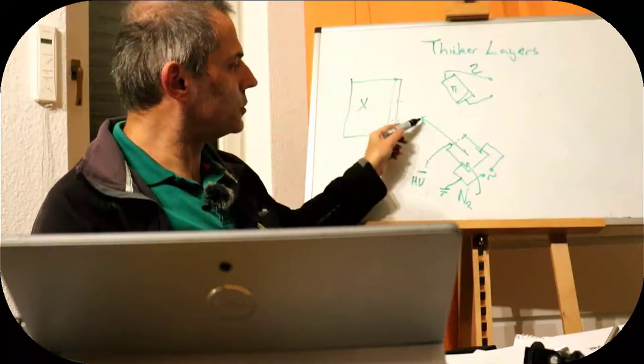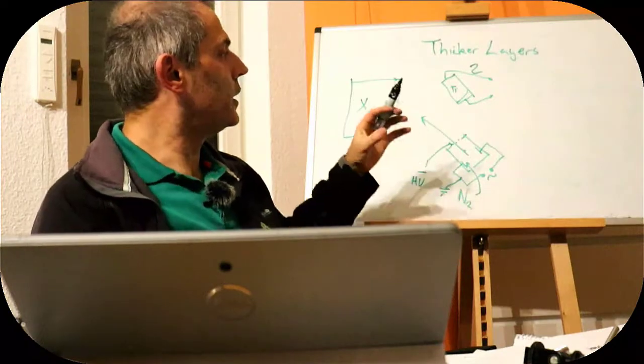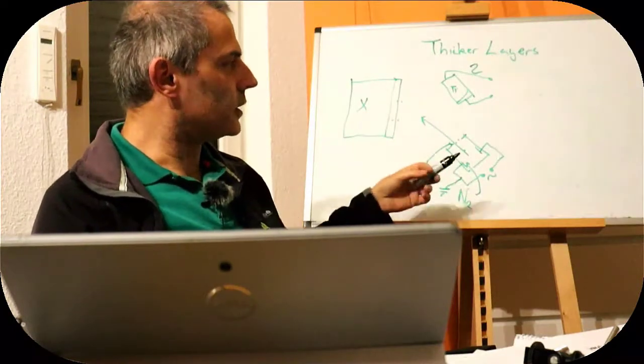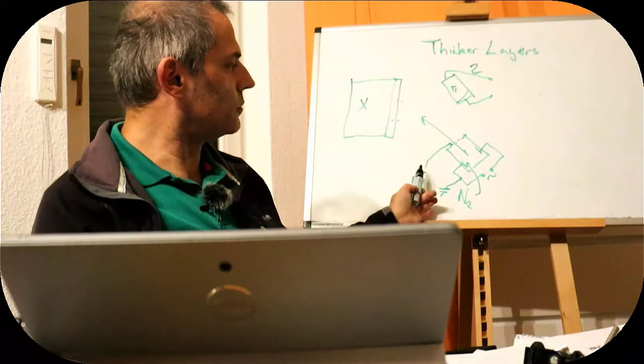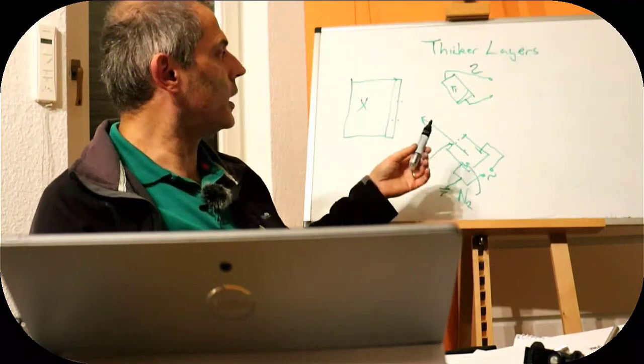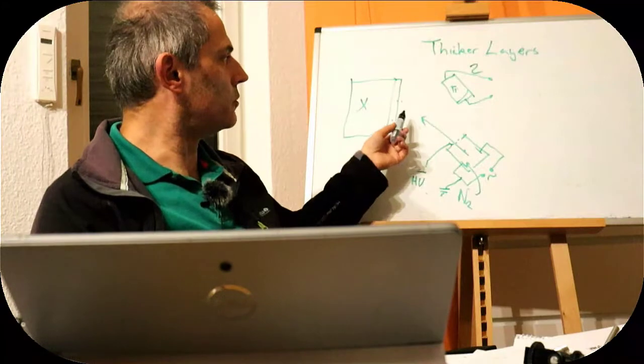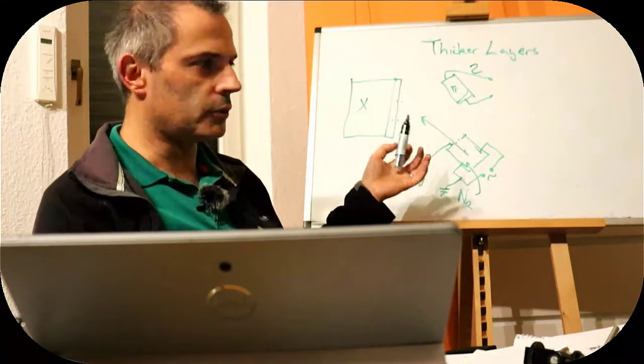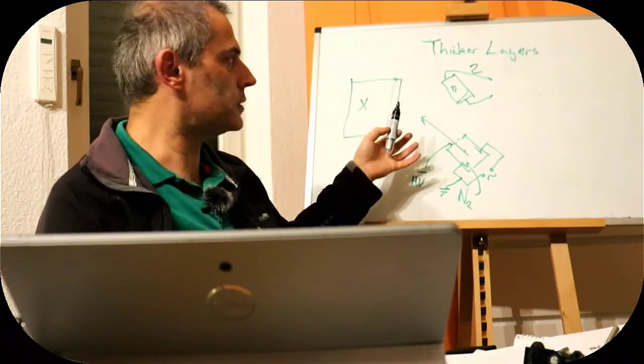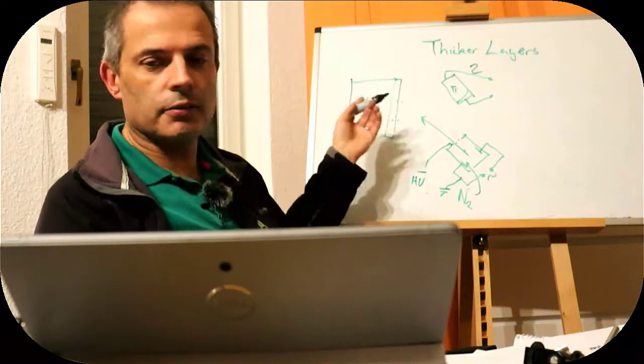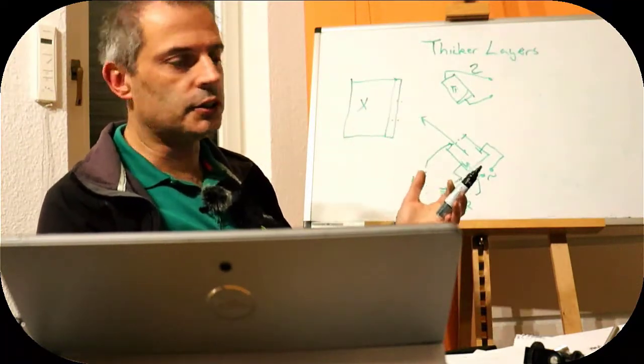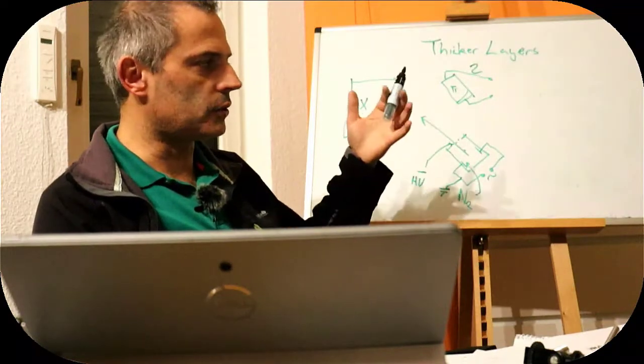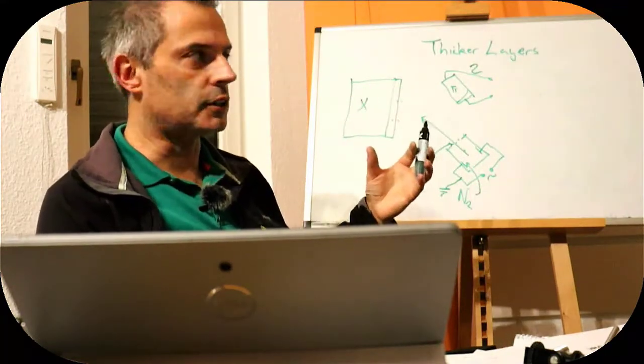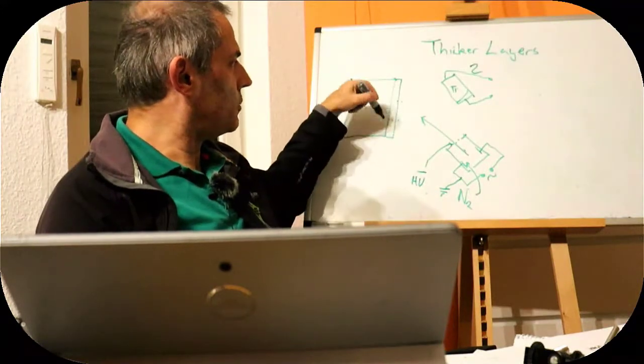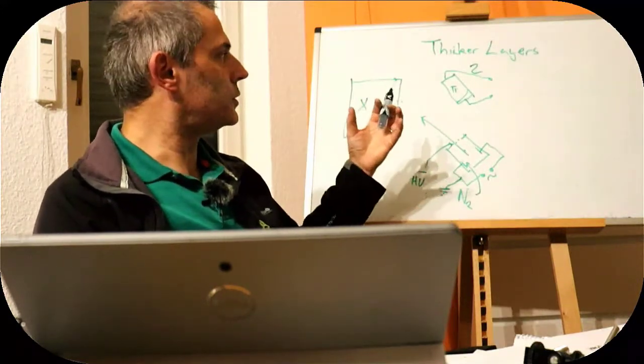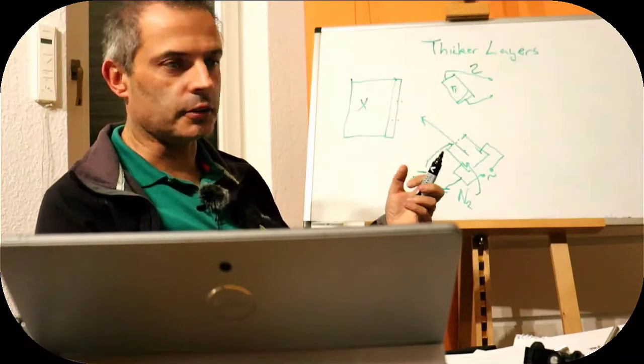And we can choose, using the length of this grid arrangement, how straight the ions are going to travel, and we can choose with the voltage how fast they're going. Although obviously if we have too much stuff in the chamber, they're going to hit something on the way, so we need to have a relatively good vacuum for this. Then we can hit the surface with a known amount of energy, which is, as with the last process of nitriding, a massive advantage for control. Then we can generate a film that we want, which is, in this case, a titanium nitride film.